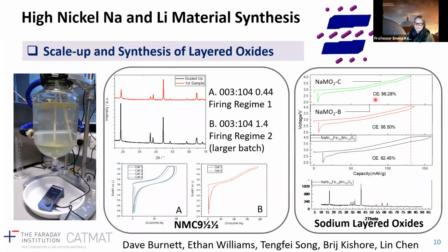And so if we consider the manufacture of these materials, I'm just going to talk about the layered oxides today, which is some work that we've been doing in scaling up both the lithium high nickel layered oxide systems and also similar sodium layered oxide systems as well. These are made in quite a similar way. And what we can do is we put metal salts into solution, then we precipitate these out as a mixed hydroxide precipitate that you can see here. The green here shows you that it's mainly nickel in this material.